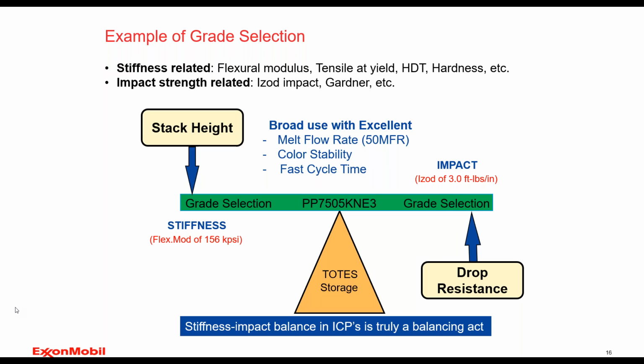The grade I pick is PP7505 KNE3, and that again is an ICP. On the green bar there, the balancing act again is stiffness to impact. And this is a level green bar, meaning it's well balanced. The stiffness can add to the stack height ability if you're stacking 4 or 5 totes high.